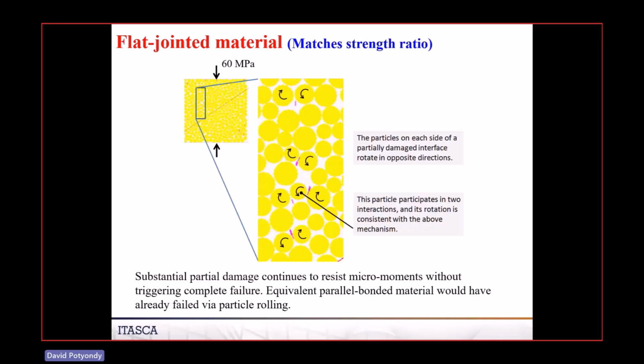And if you look, it's a very sophisticated, complicated system. This is just looking at early on in the test at some region. And if we zoom in on that and look carefully, we can see, for example, here, these two are actually rotating a little bit when you load it. There's all kinds of micro rotations that occur when you load these things. And so that micro rotation is causing tension on this side and compression on that side, and so you're getting this partial damage. If this was a parallel bonded contact, once the outer fiber reaches the tensile strength, the entire thing breaks and is removed. Whereas here, I get this distributed tensile breakage. It redistributes the load. It goes somewhere else. Here's another one that's beginning to fail.